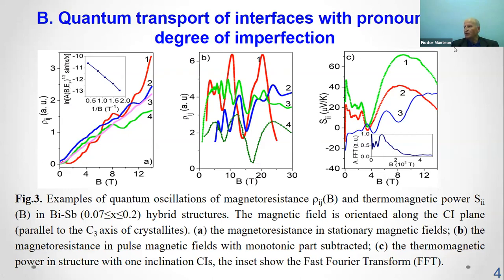It was found that the hybrid structures with pronounced degree of imperfection develop frequencies of the quantum oscillations taking different value for central and adjacent layers and also crystallite of hybrid structure. The ratio of frequency in the structures with more interfaces is lower than that in the structure with one interface.